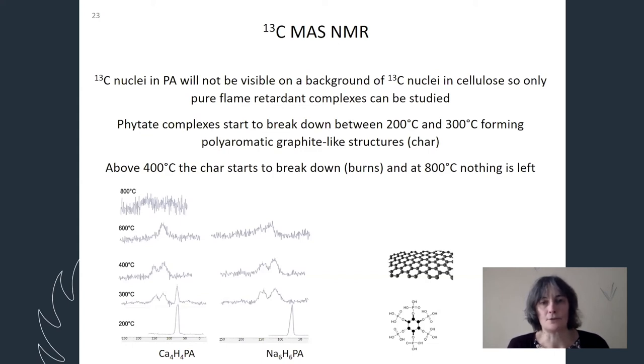At 200 degrees, the signal that we see comes from the original phytic acid sample, either calcium or sodium atoms. And then when we heat to 300 degrees, we can see that in calcium, we still have a signal at the same chemical shift, as it's called, around 75 ppm as the original sample. So we still have some calcium phytate left at 300. But sodium, then that peak position is lost. So we don't have any sodium phytate left. Instead, we see two new peaks to the left of the original one. Those peaks tell us that we have started to get some aromatic compound. So the flame retardant has broken down, the phosphorus groups have formed phosphoric acid and started to char the cellulose.